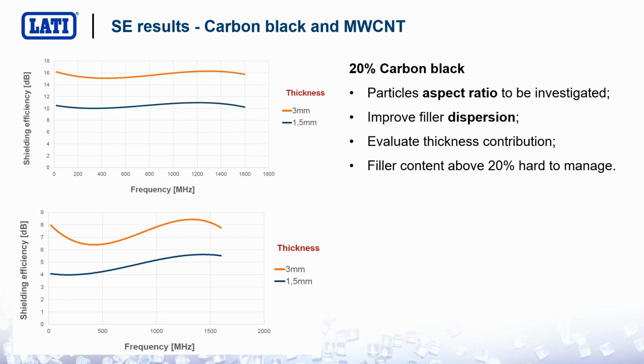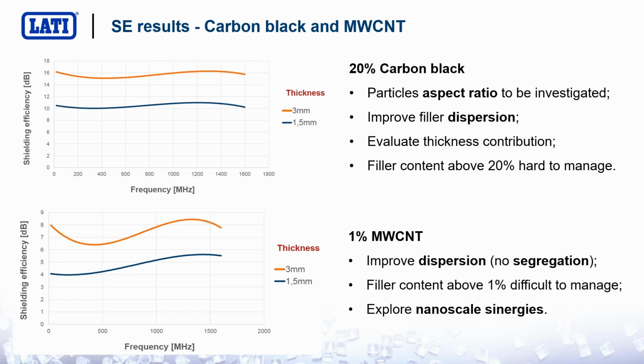For carbon nanotubes, we saw almost no benefits. But in my opinion, this was a problem of poor dispersion, because there is plenty of literature showing how carbon nanotubes and graphene can actually offer a very interesting, very acceptable shielding efficiency.